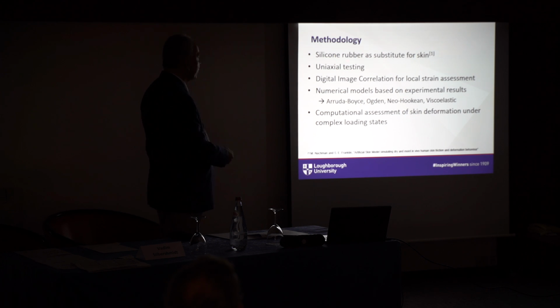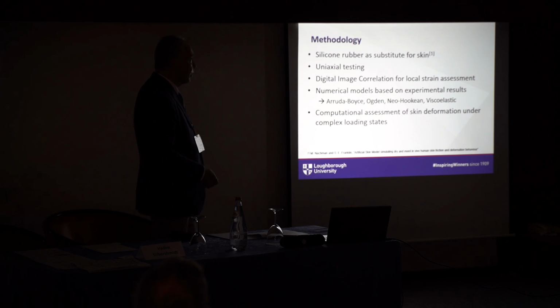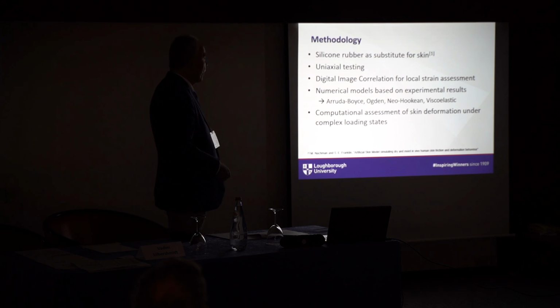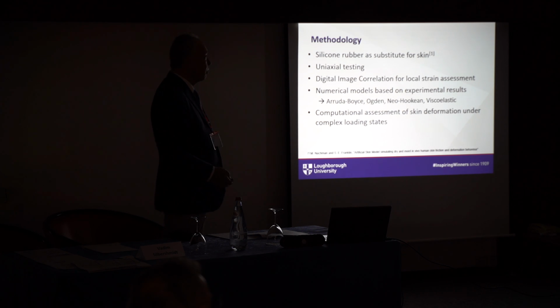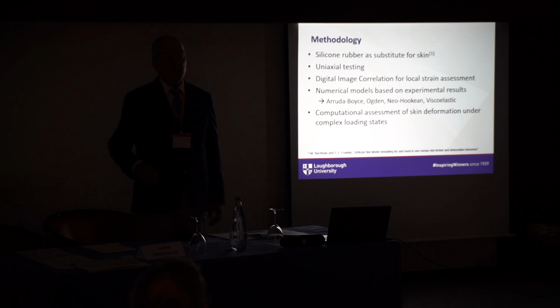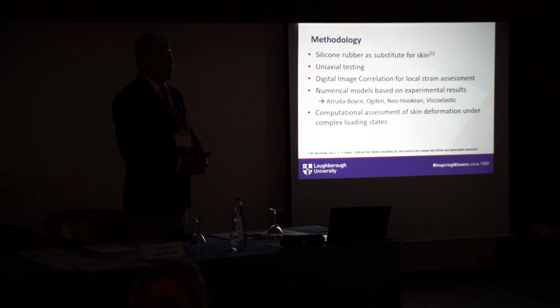We would like to introduce a substitute for skin, and silicone is an obvious case, and many people have done this. And then we would like to see how this affects the realization of the deformational process. That's why we are using digital image correlation. And later on, we will also be doing models. The names which you can see here are hyperelastic models which historically were developed mostly for polymeric materials.